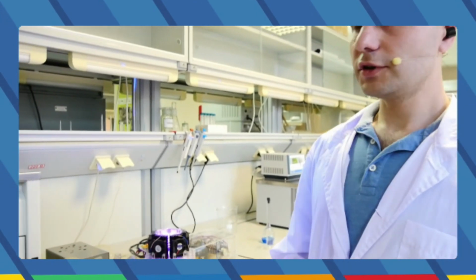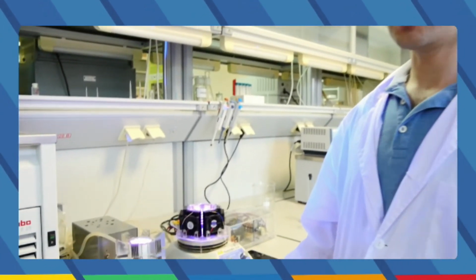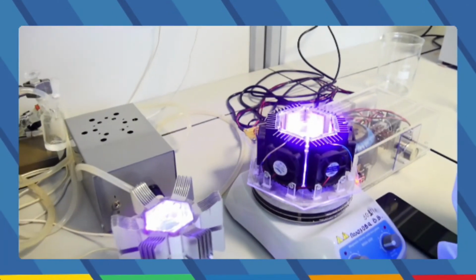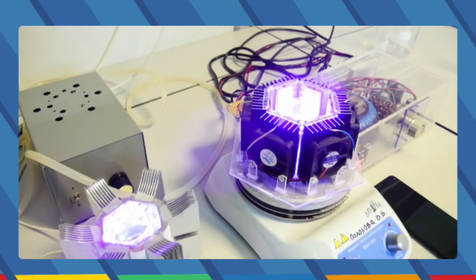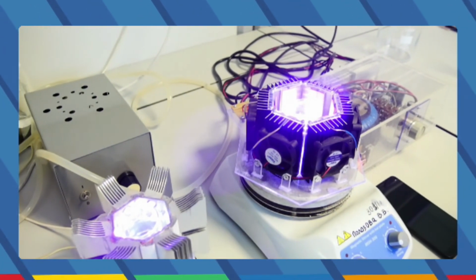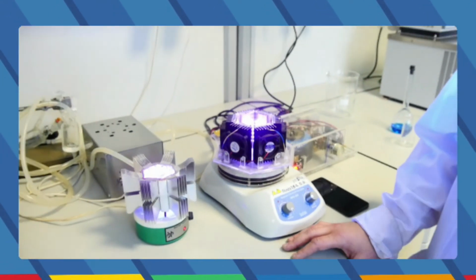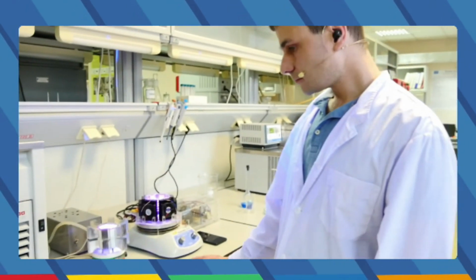This phenomena is based on the photocatalytic effect, which occurs when our material, that is a semiconductor, absorbs UV light, and in its structure begins the separation of charges. Electron goes to the higher energy level, and another charge is a hole, which has high oxidative power. So we prepared our materials from titanium dioxide, which is known to be one of the most popular photocatalysts. This compound is very abundant in nature. It's cheap enough, non-toxic, and so we use it widely for the remediation of waters and for different other reactions.